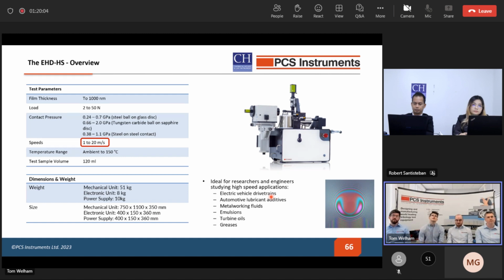So much like the standard EHD, the EHD-HS can deliver a wide range of contact conditions in terms of temperature and contact pressure. But while the standard EHD can go up to a maximum entrainment speed of 4 meters per second, the EHD-HS can reach 20 meters per second. So that makes it applicable to applications such as electric vehicle drivetrains, additive formulation in automotive lubricants, metalworking fluids and emulsions, high-speed turbine oils, as well as greases, which are particularly vulnerable to inlet starvation.